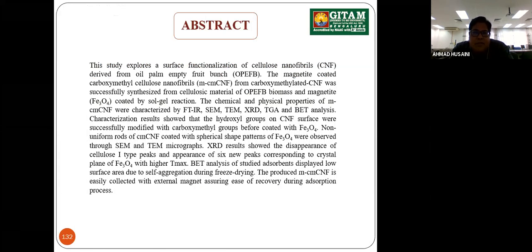Okay, so the abstract: this study is to explore the surface functionalization of cellulose nanofibril derived from oil palm empty fruit bunch. The magnetite coated carboxymethyl cellulose nanofibril from carboxymethylated CNF was successfully synthesized from the cellulosic material of oil palm empty fruit bunch biomass, and magnetite was coated using the sol-gel technique. The chemical and physical properties of the magnetic carboxymethyl cellulose nanofibril were characterized using IR, SEM, TEM, XRD, TGA, and BET analysis.